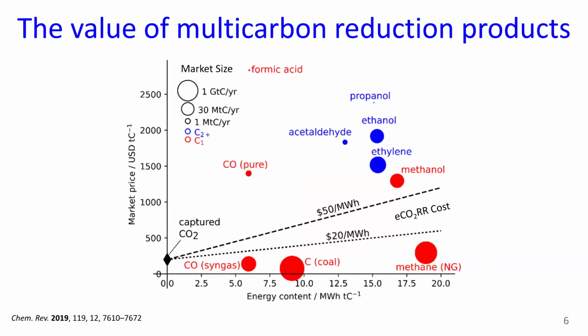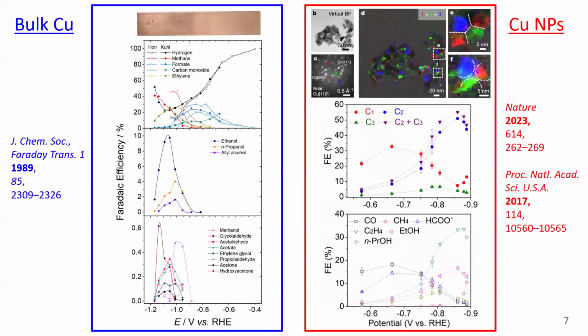And so briefly, why we're interested in multi-carbon products is that if we look at the value of multi-carbon products as compared to single carbon products, it's much more valuable to target multi-carbon products, which is why we're interested in this specific subset of CO2 catalysis. And so as you mentioned, bulk copper versus nanostructured copper, it's been known for a long time that copper is a good CO2 reduction catalyst, since the work of Hori in the 1980s.